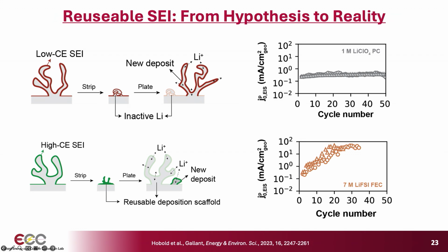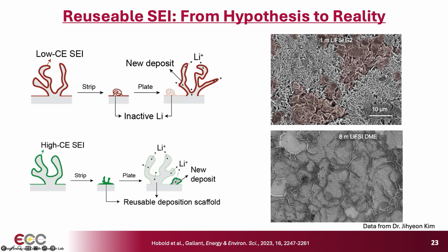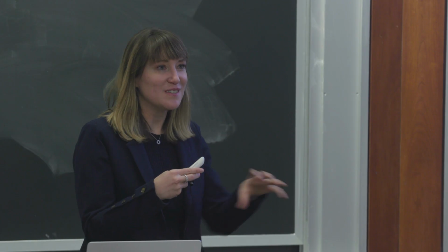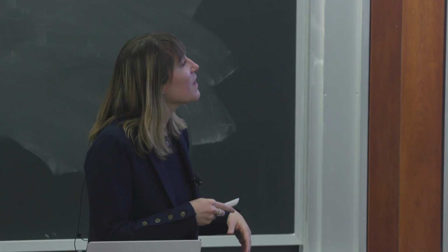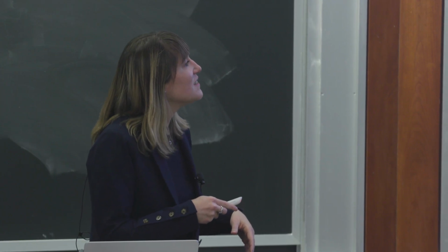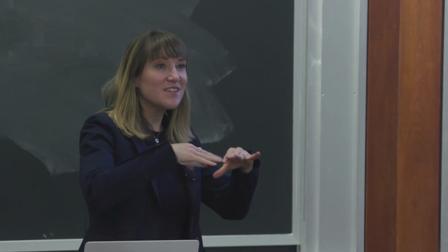So we had just proposed this at the time. We didn't have direct evidence, but I'm pleased to say that we're recently actually seeing evidence that this is really the case. So this shows on top, this is a particular electrolyte that has a low Coulombic efficiency and low J naught value. And you can actually, after stripping, see all the dead material that's kind of accumulated on the surface. And you can also visualize the stranded lithium zero that's present in the sample that we weren't able to strip out. And then for a high Coulombic efficiency, high J naught sample, we actually start to be able to